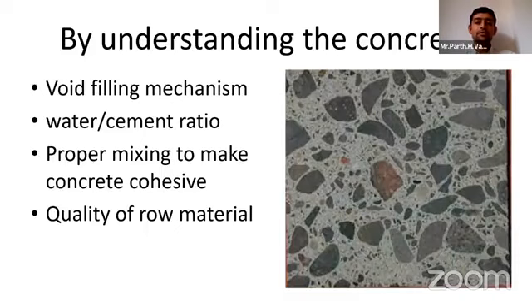For that, we should understand what is concrete, and if we understand what is concrete, then only we can make the proper concrete. So first of all, concrete is a void filling mechanism. The maximum size of aggregate in concrete is 20 mm. In general concrete, I am saying, not in particular structures like dams, where the aggregate size may go higher, up to 60 mm also. For normal concrete, which is regularly used, 20 mm is the maximum aggregate size.